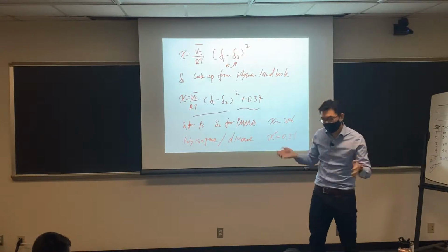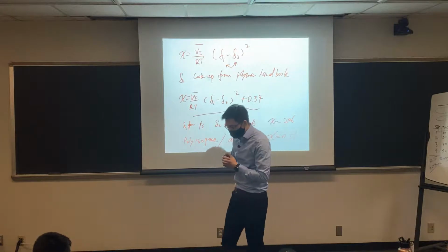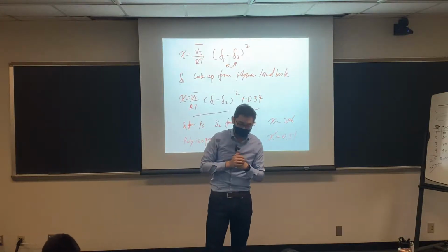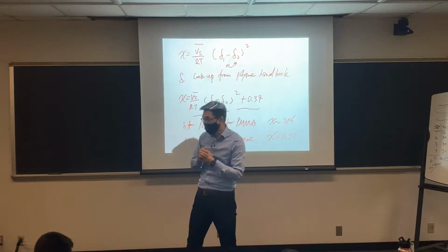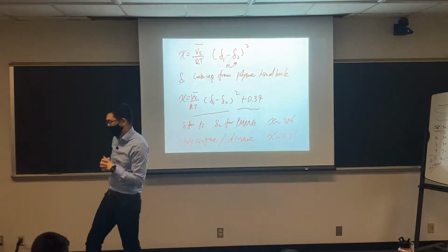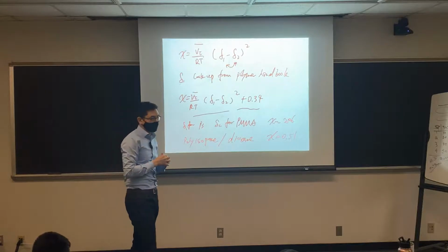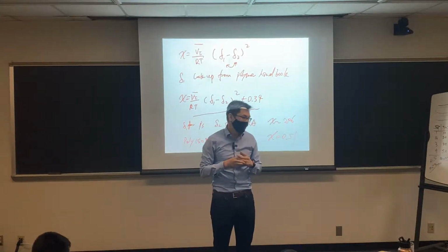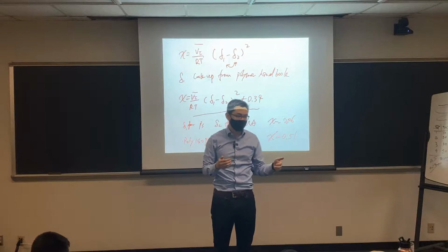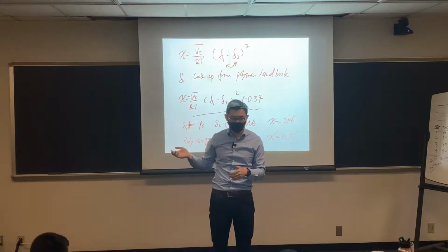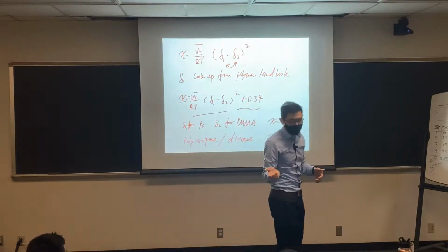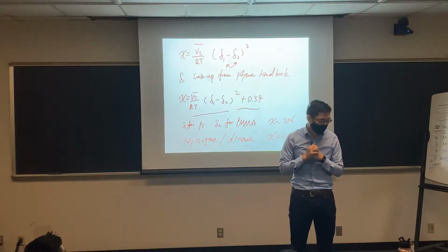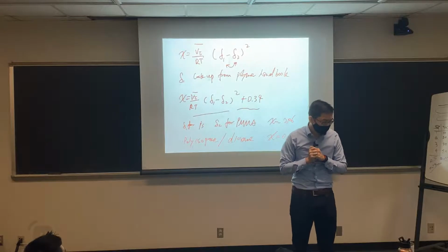So combining all together, if I'm given two materials that have already been measured, I could go to the Polymer Handbook, look at the page, say, polystyrene versus, let's say, PET. You can look at the solubility parameters and use the above equation to calculate the chi.